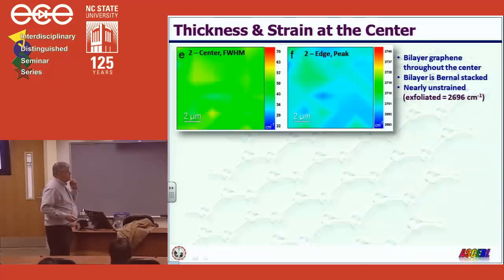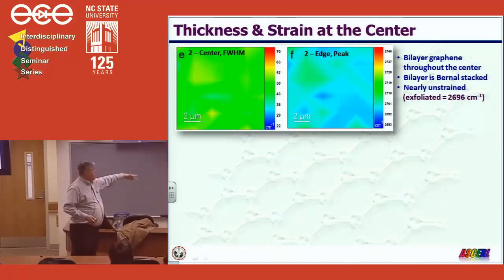And here, let's go to the center of the sample. In the center, it's all the same color in the full width at half maximum, so it's all about the same thickness. And the peak position is all in about the same position, so it's all about the same strain. It's slightly strained, but very close to unstrained.